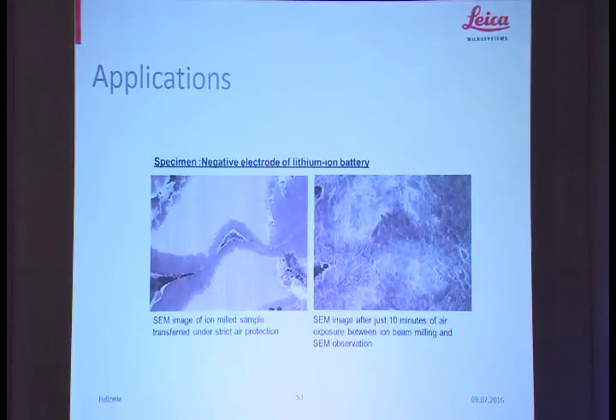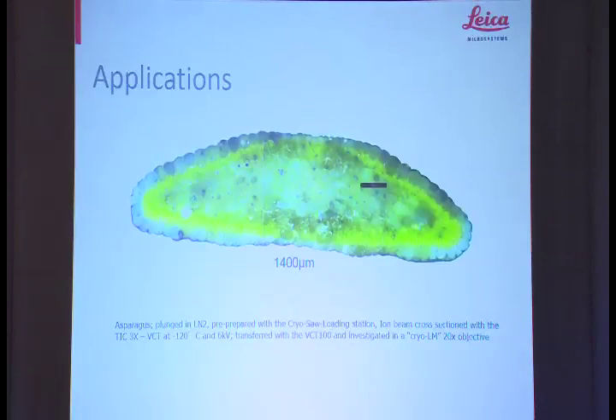And for example, lithium batteries, we don't need the cryo side, just the vacuum to hold it, preventing any oxygen getting at the sample. As you can see the difference here, this is a well-preserved sample, and this is one subject to oxygen. So lithium is highly reactive, of course. What about our biological samples? There was an unfortunate asparagus plant sitting in my colleague's office, so we utilized the leaf of the asparagus plant for our first experiment. And as you can see, we ion beam milled after freezing the whole of a cross-section of a leaf. So this was a good step into the direction we wanted to go.